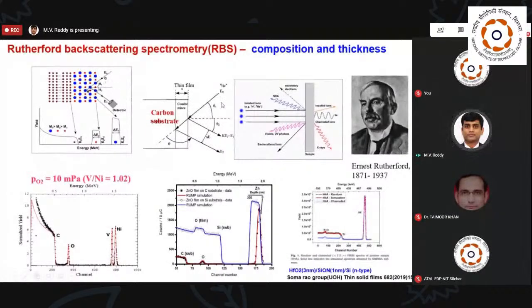So depending on the energy and depending on thickness, there is a kinetic energy E1 and E2. What happens is that depending on the atomic mass, for example, the higher atomic number mass comes first, followed by lower atomic number. So it is a typical RBS spectra, the simulated spectra using nickel, vanadium. The advantage is that we know what type of composition, or if there is any impurity. So it is the best technique, and we can also see nitrogen, carbon and oxygen.